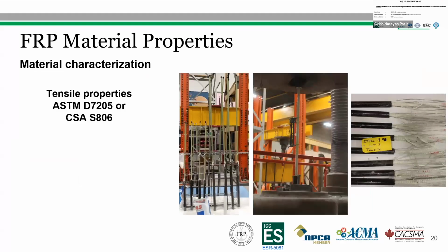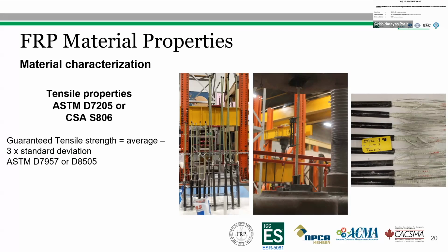The tensile properties of the GFRP specimen were tested in accordance with ASTM D7205 or CSA S806. The test specimen was prepared by installing a steel tube on both sides of the FRP bar using expansive cement. The tests were performed on a Baldwin testing machine, and the test load was applied until failure occurred.